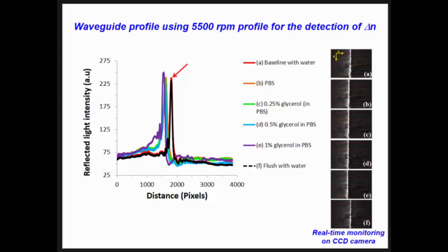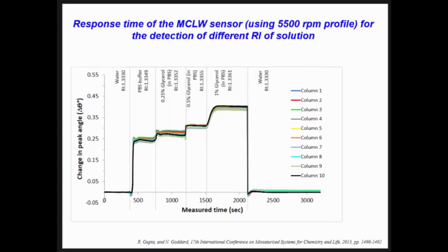If you can see here, I just want to highlight from the baseline with water, you see this is the peak, but at the end of detection, after we change a few buffers here, at the end we flush away with water, we can see it remains at the same position. So this is what we monitor on the CCD camera. So meaning that the binding is so good, and the hydrogel fits very well on the substrates, and it does the job. And in terms of real-time monitoring, this is the response time when we convert to the change in the angle. Each of the buffer changes is good, and shows the diffusion time is very short.